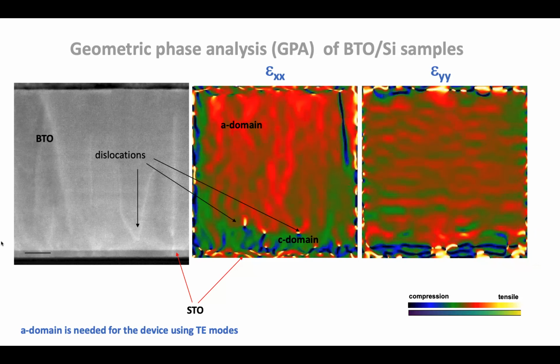But as I go thicker, I get this sort of a domain, meaning polarization is now in plane, which is what you want for TE modes, right? Because my light goes this way, polarization is that way, so the ferroelectric polarization should be in the same direction. But you can see it's a complicated thing, and I want to understand how that controls the electro-optical response.